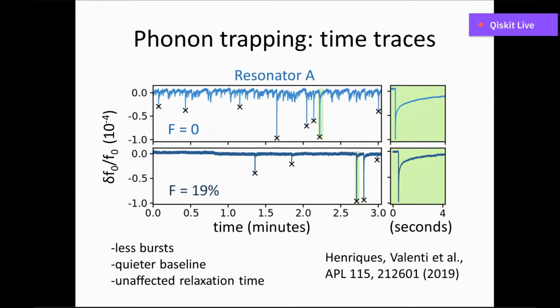This is the same setup with 19% coverage, 19% filling factor of phonon traps. We can appreciate that the baseline of the fluctuations of the resonant frequency gets quieter. We observe fewer quasiparticle bursts, all the while maintaining the same relaxation dynamics for the quasiparticles.